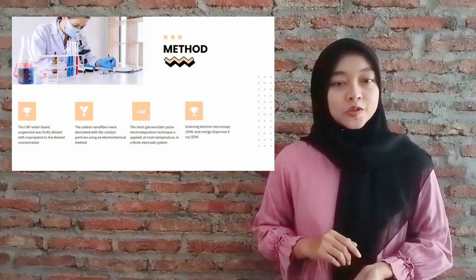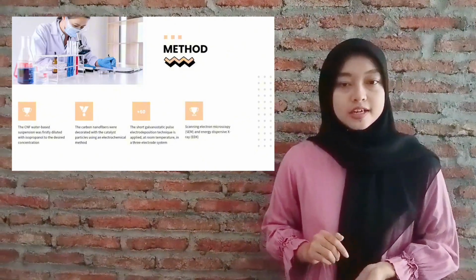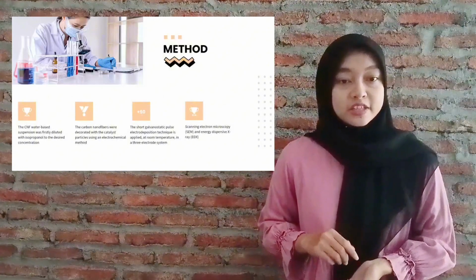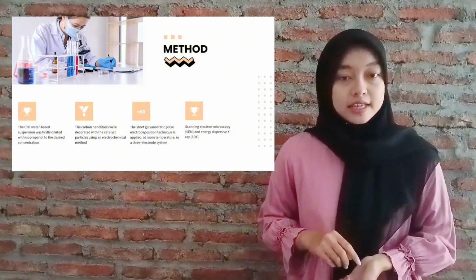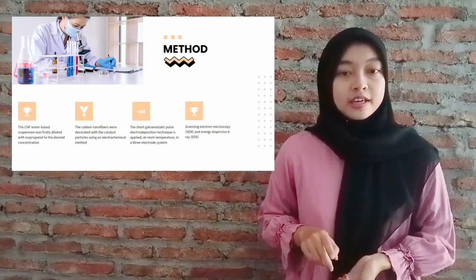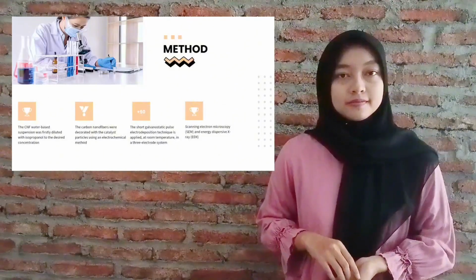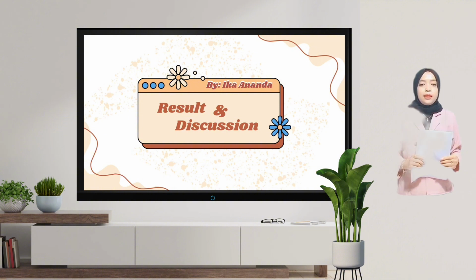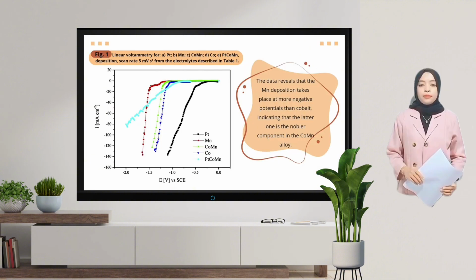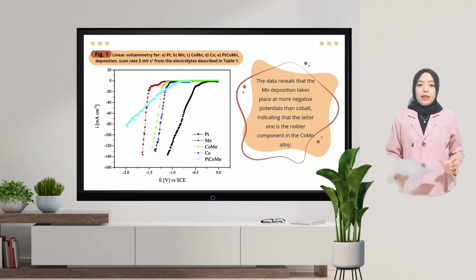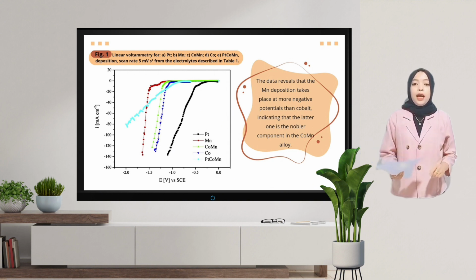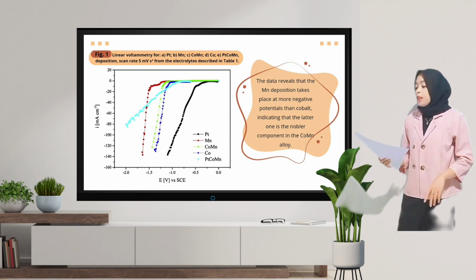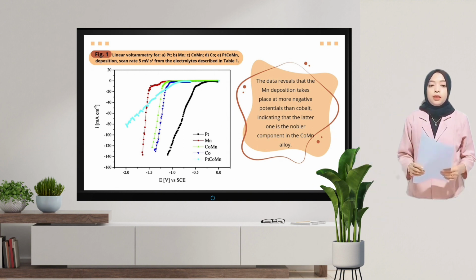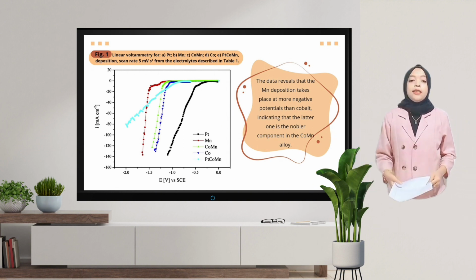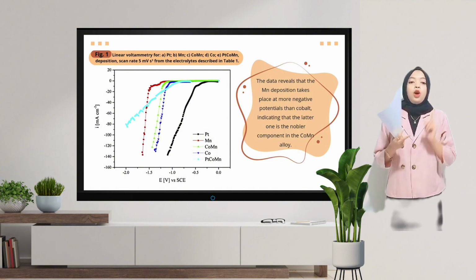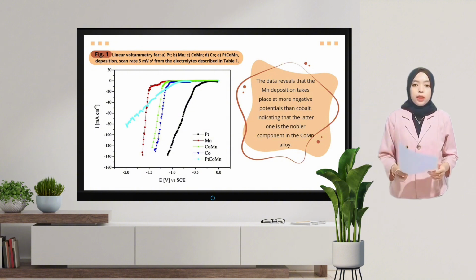Scanning electron microscopy and energy dispersive X-ray spectroscopy were carried out to reveal the catalyst morphology, structure, and chemical composition. Okay, then I will present result and discussion. Before the deposition of the platinum, cobalt, manganese ternary alloy was carried out, typical potentiodynamic cathodic polarization curves for the deposition of the single metals platinum, cobalt, and manganese were recorded.